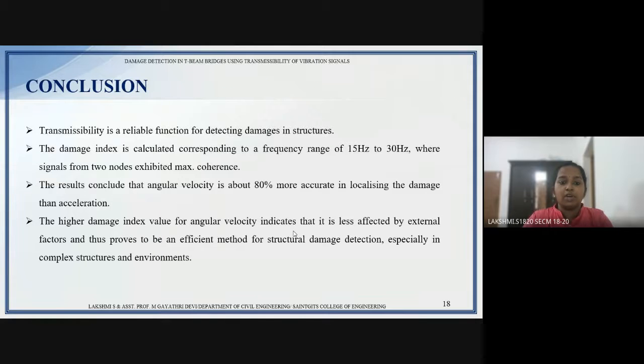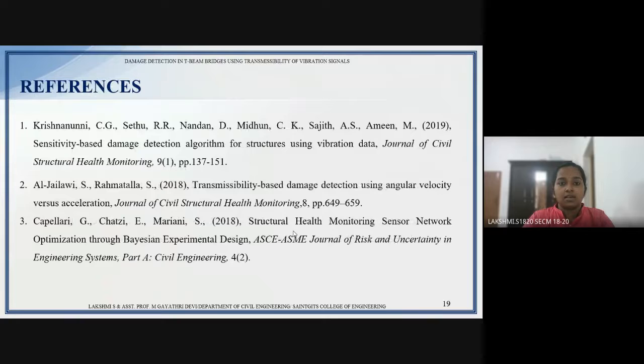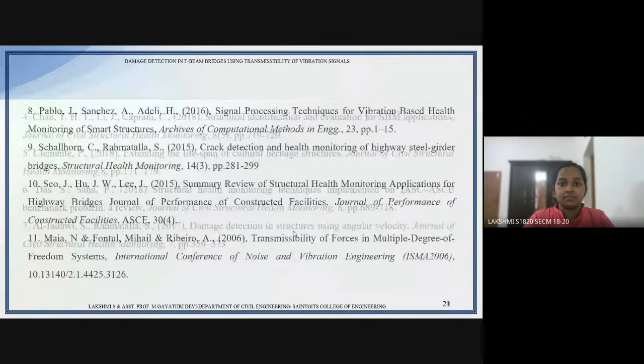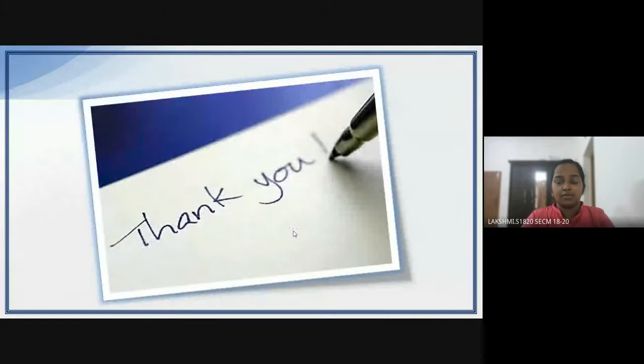So we were able to conclude that the angular velocity based damage index calculated was almost 80% more accurate in localizing the damage than that calculated based on acceleration. And thus we were able to conclude that transmissibility based on angular velocity is a reliable function for detecting damages in structures and also in complex structures like bridges. So these are my references. Thank you.